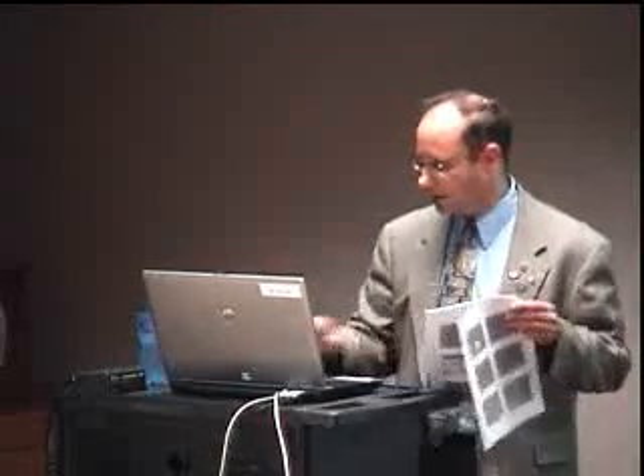The joint spacing actually varied quite a bit. Towards the west end of the bridge it was an 84-inch spacing, and towards the east end it was 140 inches. And as you'd expect, once you go to the larger joint spacing, you start to see a lot more mid-joint cracks in between. And that was the most severe of the 4 bridges that we looked at in the course of this study.